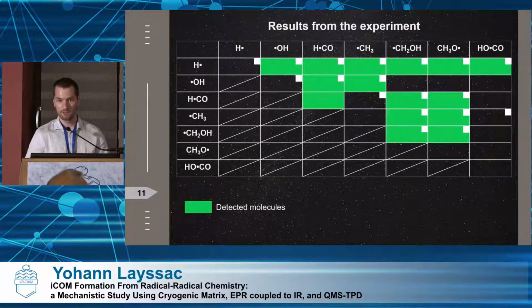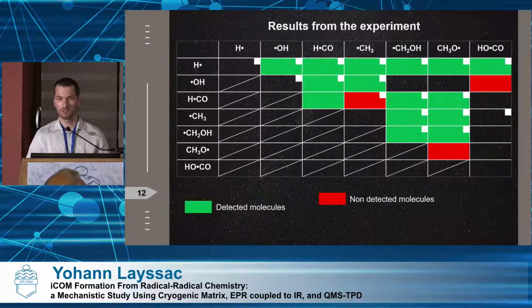So it's interesting, we see most of them, but maybe most interestingly, we don't see some of them, the red ones, telling us that the radical plus radical reactivity is not always working for these molecules, at least. And especially for the acetaldehyde case, a molecule usually detected in the ISM, we don't form it in our experiments. So the question is why we don't see acetaldehyde and we see glycolaldehyde.